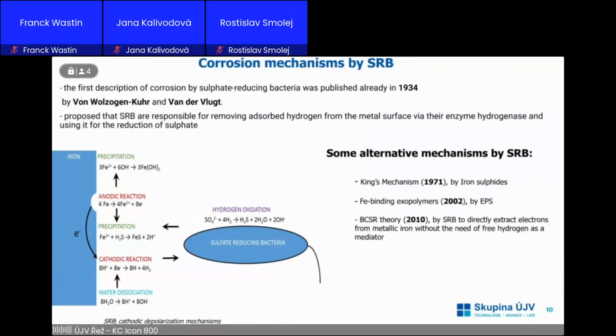Here you can see corrosion mechanisms by sulfate-reducing bacteria. There are some alternatives. In the figure you can see the mechanism of cathodic depolarization, which was first described and published in 1934 by von Wolzogen Kühr and van der Vlugt. They proposed that sulfate-reducing bacteria are responsible for removing adsorbed hydrogen, which increased the cathodic reaction and that led to an increased anodic reaction and so the corrosion rate. Another alternative is King's mechanism from 1971. They showed that corrosion is also accelerated by iron sulfide, which is more noble than iron oxide, and the corrosion was increased due to the galvanic effect.